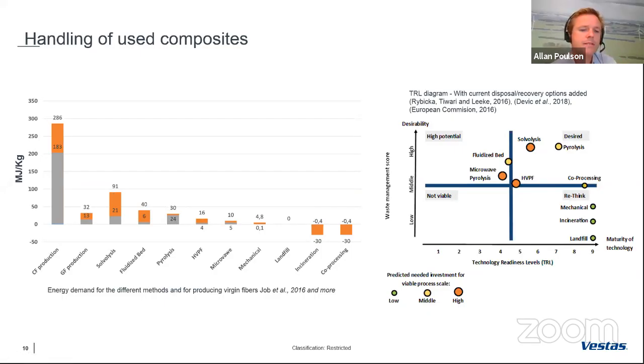But what you will see is that it's actually more energy demanding to do solvolysis or fluidized bed or pyrolysis recovery of the fibers compared to just production of a pure virgin glass fiber. And that is really one of the issues. We need to drive this energy consumption down, and of course the energy needs to come from renewables. So these are some of the issues.